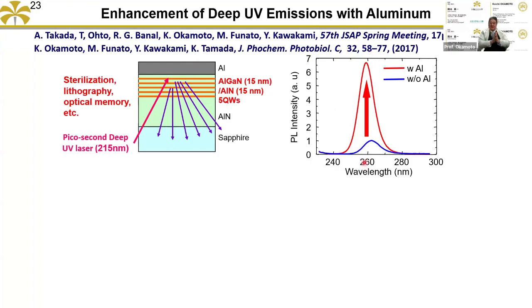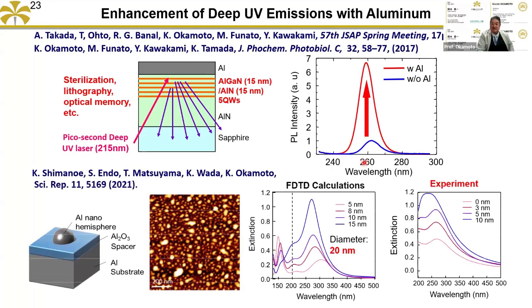We also want to extend to even shorter wavelength regions. Then we fabricated this kind of NHOM structure, nanohemisphere on the substrate. In the calculation, the peak was split into two, and the shorter one reached 150 nanometers. That shorter wavelength is maybe the shortest record in the world for surface plasmon resonance. That's the calculation, and that one is the experiment. We can also obtain the split into two. But unfortunately, our equipment has difficulty measuring wavelengths shorter than 200 nanometers. But you can see it begins to separate into two, and maybe another peak must be there.